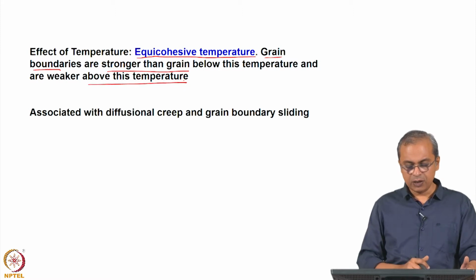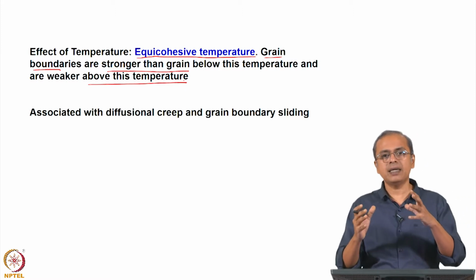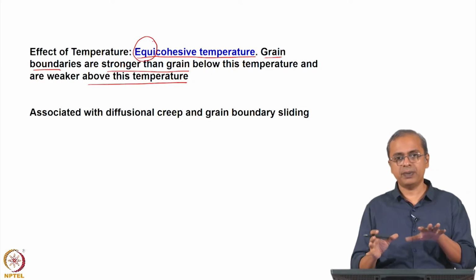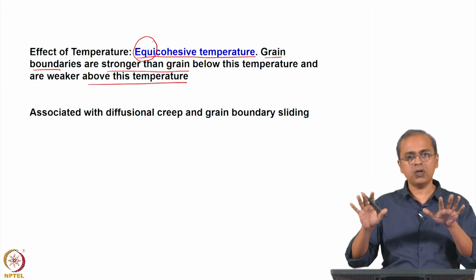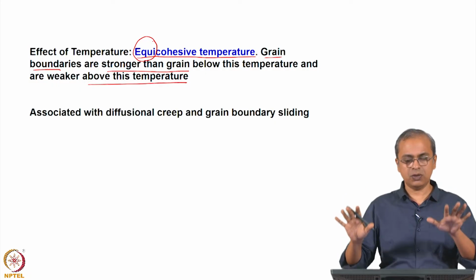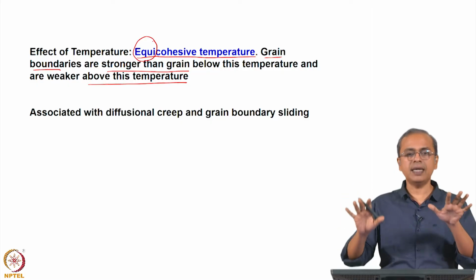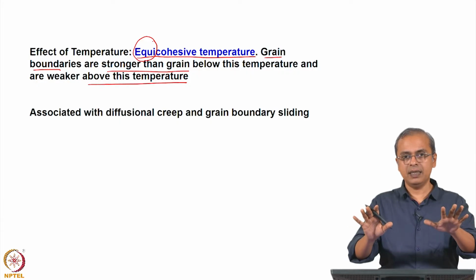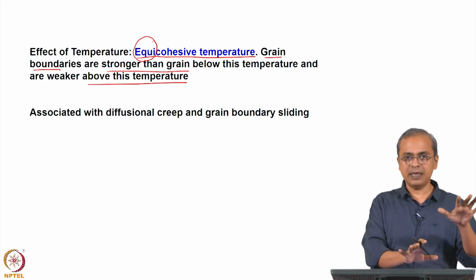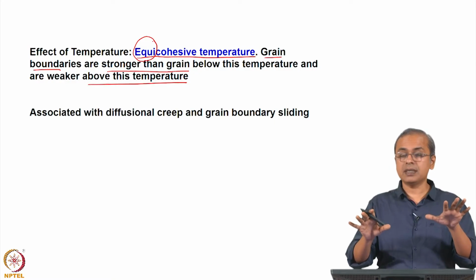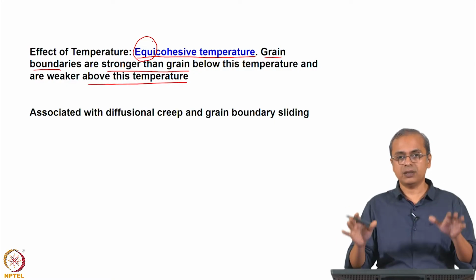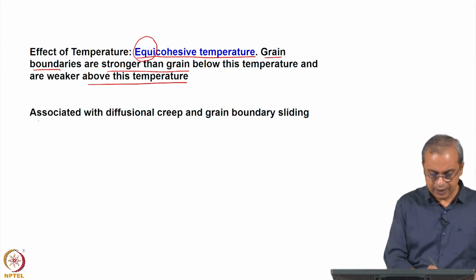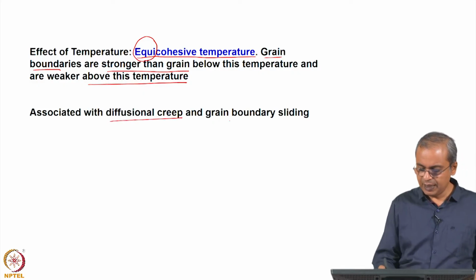Okay. So, the equicohesive temperature is a temperature where the term equi means something is equal. It means that at the equicohesive temperature, the grains are roughly as strong or as weak as the grain boundaries themselves. So, both the interior of the grain as well as the boundary have roughly the same contribution to the strength of the material. If you go below in temperature, the grain boundary becomes relatively stronger than the grain. If you go above in temperature, the grain becomes stronger than the grain boundary, and so correspondingly you see a difference in behavior. This was explained by creep, diffusional creep and grain boundary sliding.